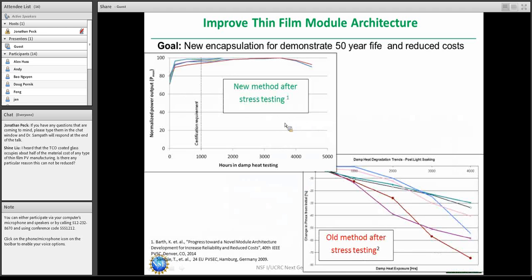Now, this package has been put together and has been tested. So here is the new method I described to you before, tested for a large number of hours in what is called damp heat testing, where there is high humidity and high temperatures, and you look at the power output of the module as a function of time. And as you can see clearly here, it goes on up to 5,000 hours with not much